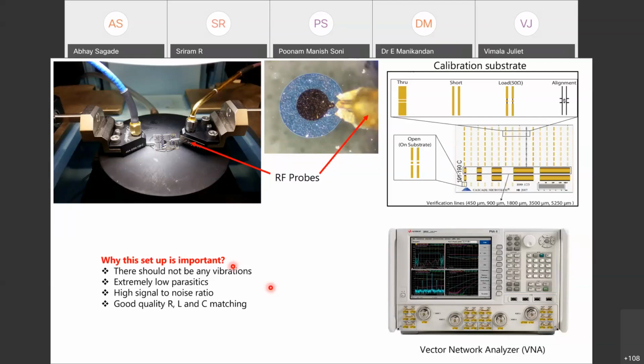Now, why this setup is important is because there should not be any vibrations. It should have extremely low parasitics, a high signal to noise ratio, and very good LCR matching. All these parameters you can actually subtract from the environment using a calibration of the device. This is a very important step before starting your measurements. Each and every time your setup should be calibrated. So this is a standard chip which you can buy to calibrate your device. And this is the second unit, called a vector network analyzer, which is required for measuring its intrinsic performance.